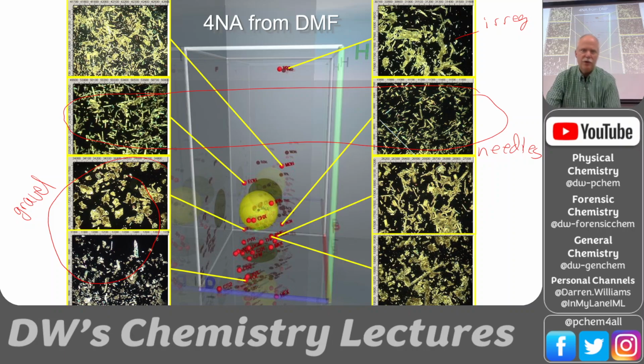Now, just forensically, I want to point out that this is the same chemical structure, right? So if we did a chemical analysis of these different samples, we would get the same answer. Same FTIR, same mass spec, all of that. So the chemical properties are not any different no matter which path we had. Now, okay, maybe we could get residual solvent. So maybe from this one we would see residual toluene, and maybe from this one we would see residual acetone. And so a residual solvent analysis might be able to reveal that these were processed differently. So that might be a chemical signature that we can say this powder and this powder are different. They have a different origin.